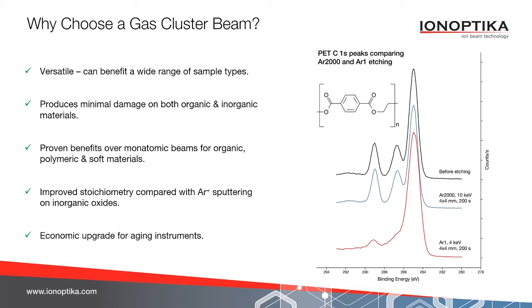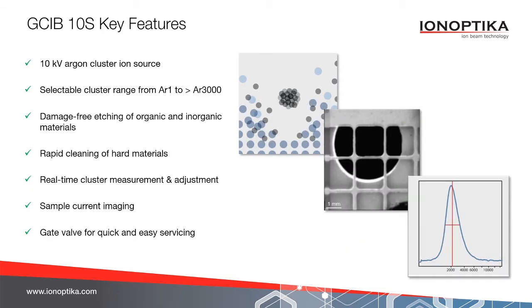The GCIB itself is a very economic upgrade for aging instruments. It can provide a means of extending an instrument's life because it introduces a new means of analysis, whether that be depth profiling, whether that be sample cleaning, etc. So the GCIB 10S itself is a 10 kilovolt argon cluster ion source. We provide a range of presets which allow the user to select the cluster range all the way from argon 1 to more than argon 3000. In most cases, if the user requests it, we will provide argon 4000 or even argon 5000 as well.